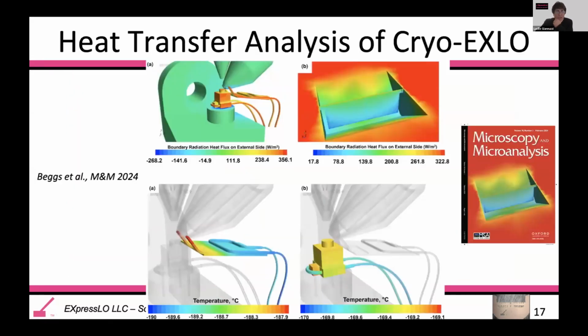So one of the first things we had to do, in conjunction with the experimental, was make sure that the geometry of a cryo ex situ lift out FIB specimen would remain vitreous. And so our partners at Center Corp, Kyle Beggs and Alan Kassab, worked with us to do heat transfer analysis of essentially the FIB-SEM geometry and a cryo stage.